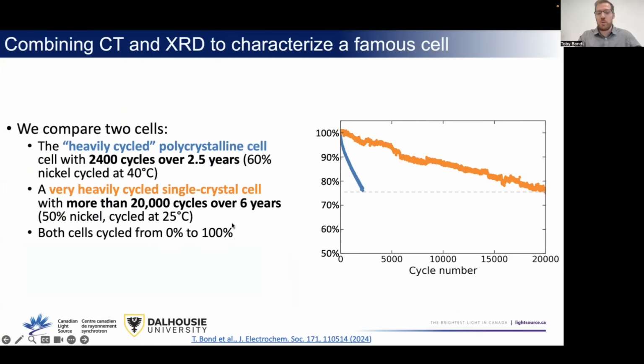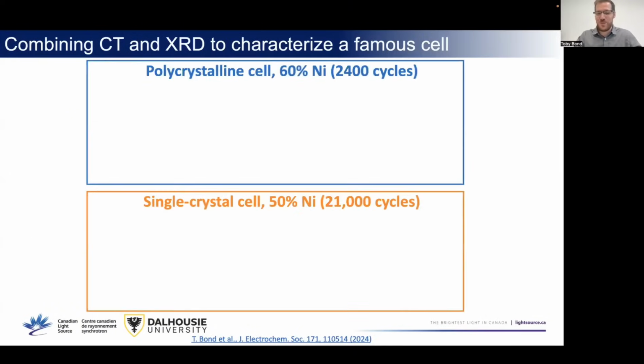And this is deep cycled. Both of these batteries were deep cycled. So this is the heavily cycled cell I was just showing you in blue, and that's how fast it degrades, which again, isn't fast. It still lasted a good while and it was abusively cycled, but the single crystal material just does so much better. It has roughly 10 times the number of cycles, and it reached the same amount of capacity fade, and probably still has a lot left to go. It's still cycling in the lab as we speak. So yeah, it's just amazing how good that capacity is after so much time.